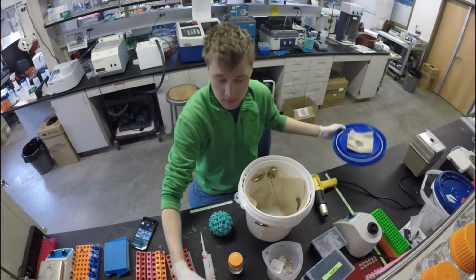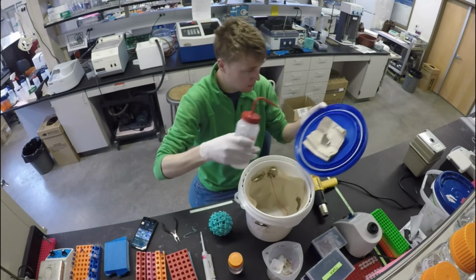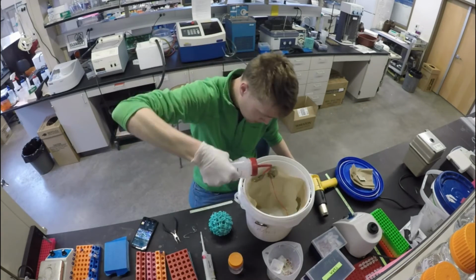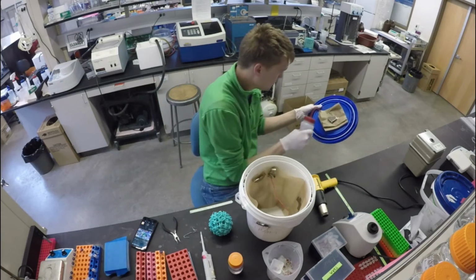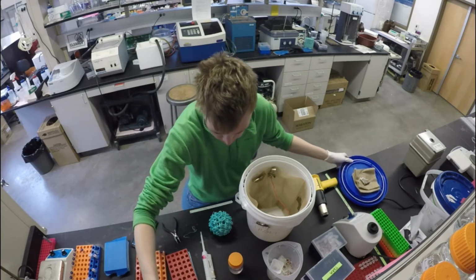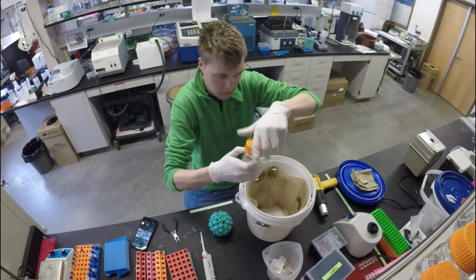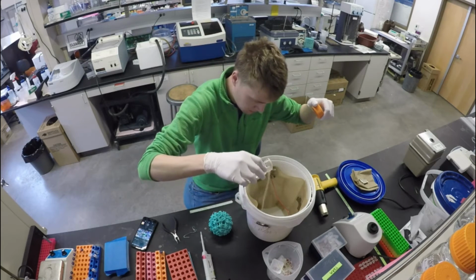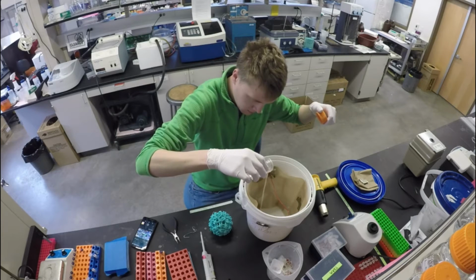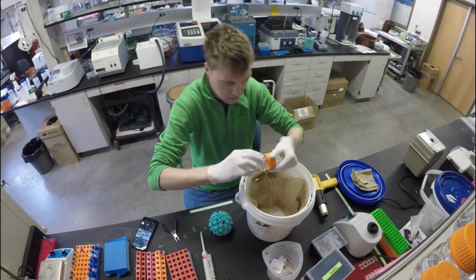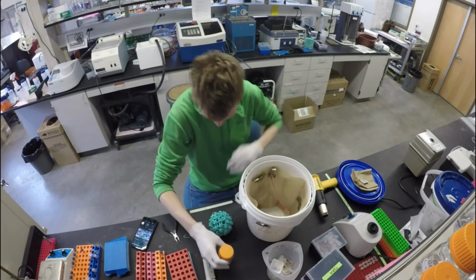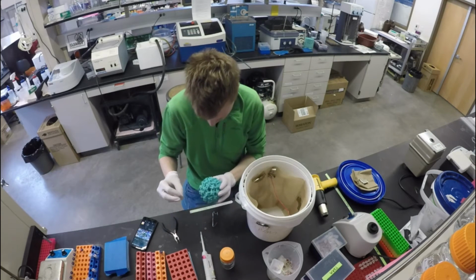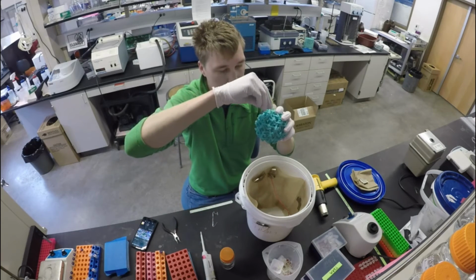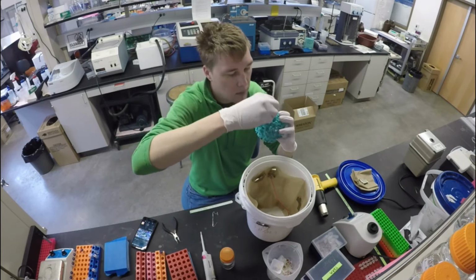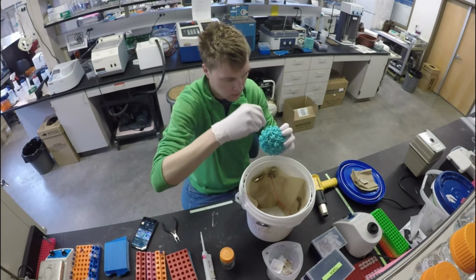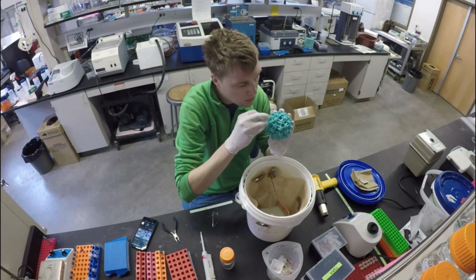That's my bucket. I've got some magnets holding paper towels to the sidewalls and a little wire. I'm going to apply some acetone to the entire walls and the lid where I've got the paper towels. Apply a little bit of acetone to the bottom here. And I guess I just went with the whole thing. Basically, what we can now do is hang our part inside of this chamber, and the acetone fumes will melt the plastic, and they'll do so in a very slow way. So it's a process known as annealing.